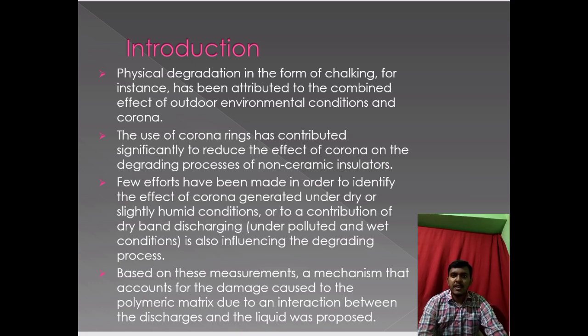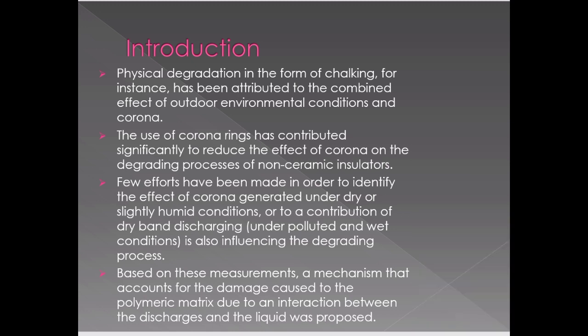It is also a well known fact that the exposure of dielectric surface to corona gives rise to space charge, and the rate at which the space charge accumulates within the polymer depends on the type and magnitude of applied electrical supply. This defines the extent to which corona discharges may provoke the degradation of polymer physical and electrochemical properties. According to the reports, the average lifetime of polymer insulator used in a DC system is expected to be shorter in comparison to that of an AC insulator, and that will be explained in the upcoming slide.